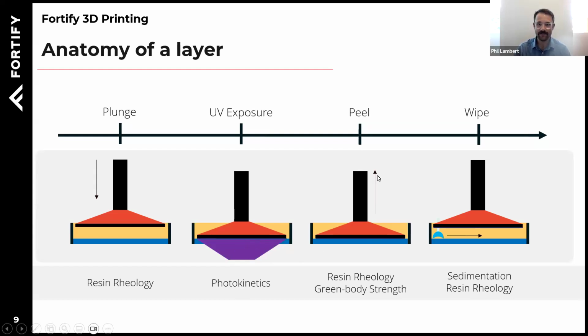And then we peel that cured shape off of the film that sits in between the build plate and the glass. And then resin flows back into that interstitial space to repopulate that area with uncured resin. And then we repeat, except this time we plunge again 2 layers above the glass. So now we're selectively curing a new layer of material onto the previously cured layer. So that's how this technology works.